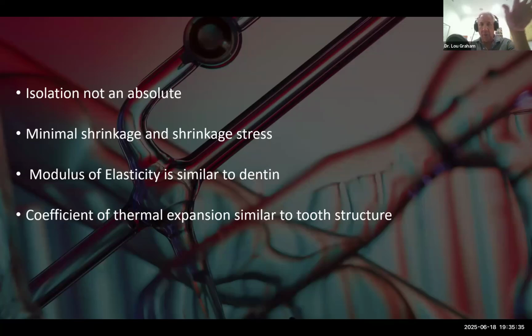There you are working in your oral environment, and oftentimes you can't isolate an area. Isolation is not an absolute with glass ionomers. They can be delivered in slightly moist environments. They have much less shrinkage and less shrinkage stress than traditional composites. They have a modulus of elasticity similar to dentin, meaning the flexibility, and their thermal expansion, hot and cold, very, very similar to tooth structure. This gives them distinct advantages over composites.